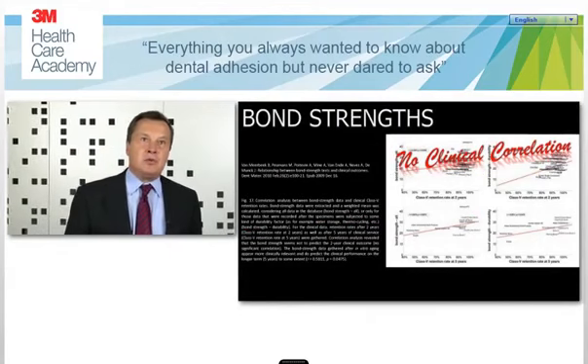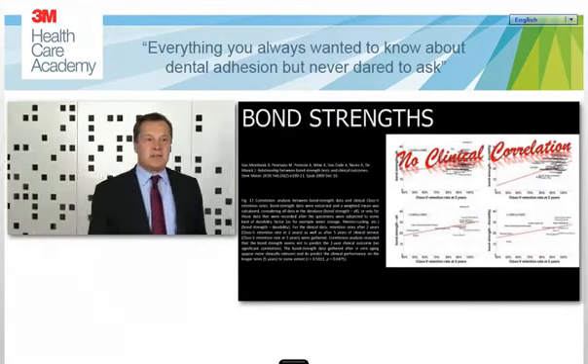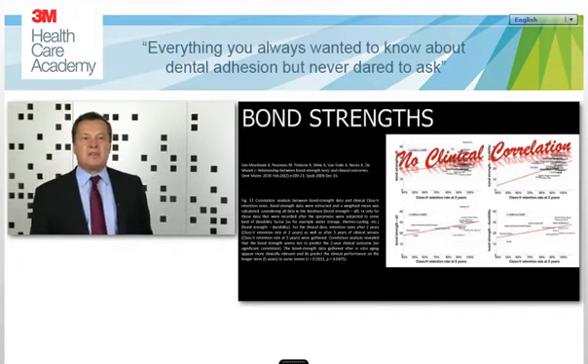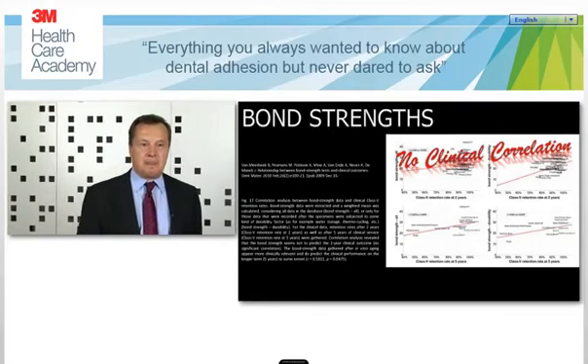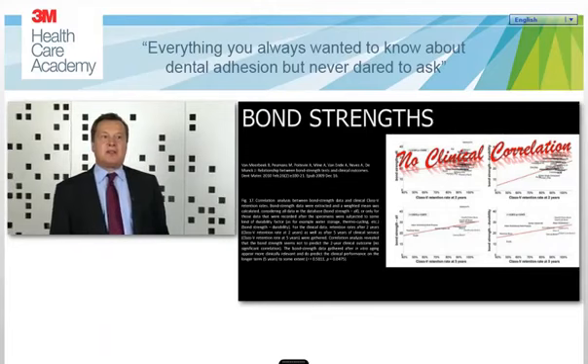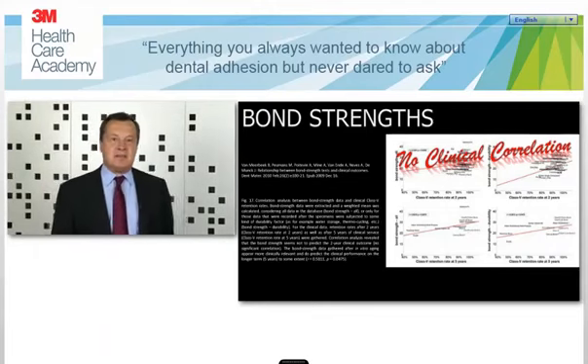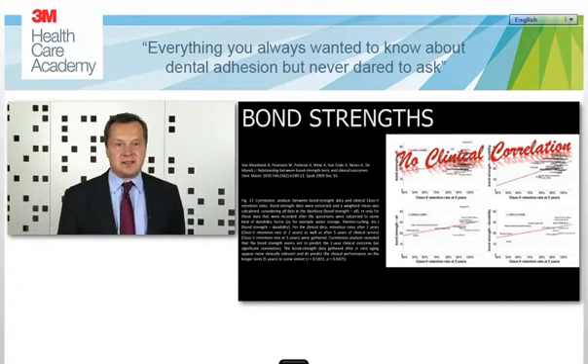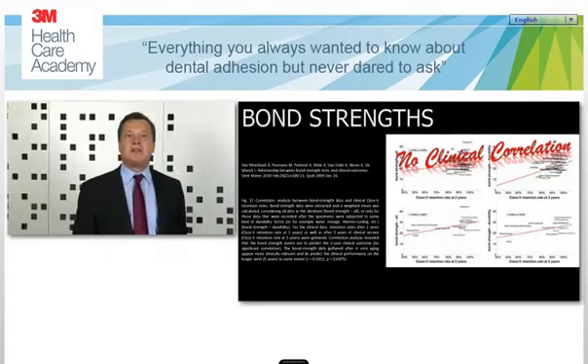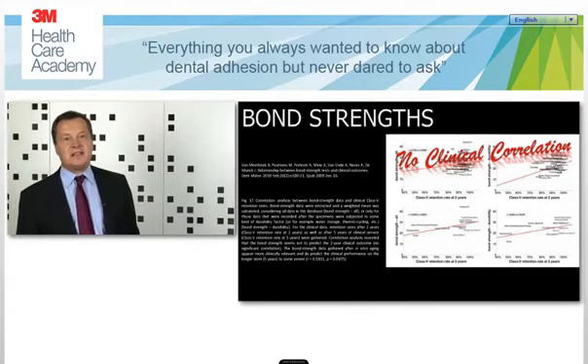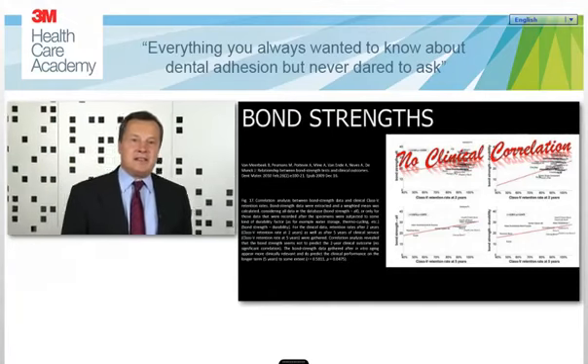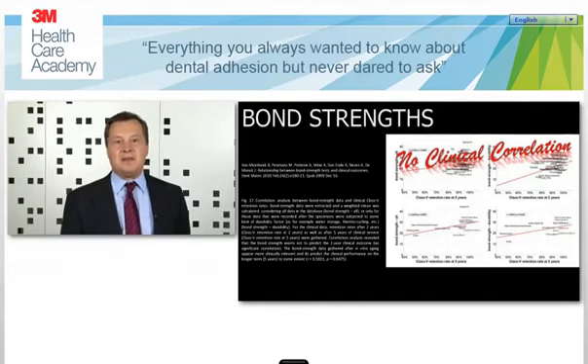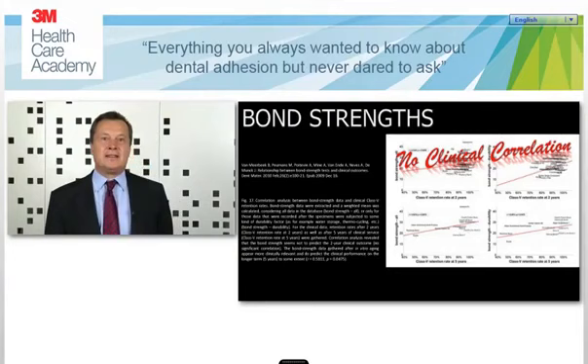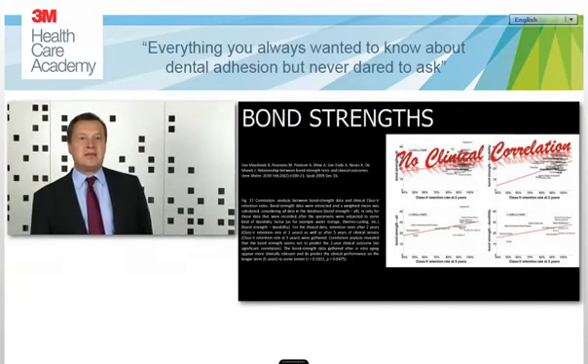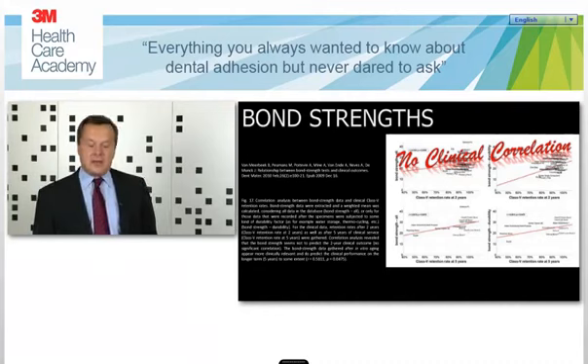What if you would like to know what is a good adhesive system and what is a less good adhesive system? The question is, what is the reliable data you should have for that? Many people rely in this perspective on bond strength, and they think that if an adhesive system has a higher bond strength, it will behave better in the clinical situation. Unfortunately, there is no clinical correlation between bond strength and clinical performance. So to classify adhesive systems according to bond strength is not a very good idea, meaning that if you choose your adhesive system based on bond strength, you will not get really the relevant information for clinical behavior.